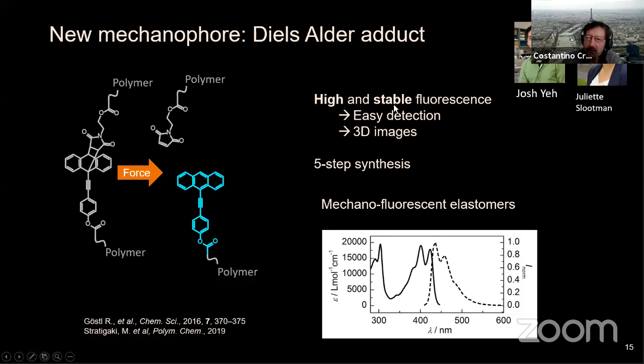Now, the biggest difference is that the fluorescence that it gives out is very stable and high intensity. So it gives you a detection threshold which is much, much lower. You can really detect the molecule at least two orders of magnitude lower in concentration. And because, if you don't look at the propagating crack but a static crack or a fracture surface, you can also do 3D images. So this shows you basically the principle. You excite the molecule around 400 nanometer with a laser, and then you collect the signal around 450. So we can do this quantitatively, again, with a confocal microscope.